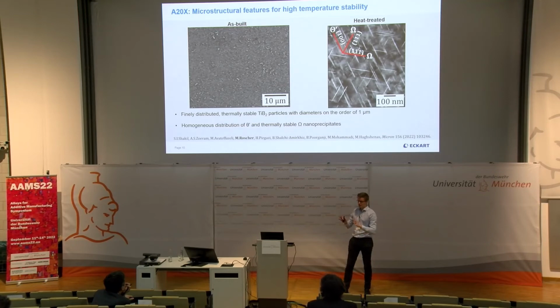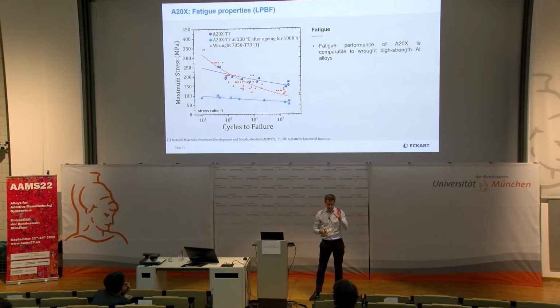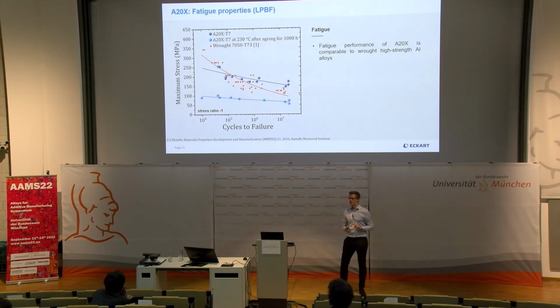And all of these comments were on strength. Now, especially in the aerospace industry, many catastrophic failures have occurred due to cyclic loading, fatigue failures, rather than simply overstressing a component. So fatigue performance is critical and a requirement if we want to exchange conventionally produced components with LPBF produced components. In this figure I have included two types of A20X fatigue data points. Dark blue is standard room temperature fatigue testing. So LPBF processed, heat treated, machined.